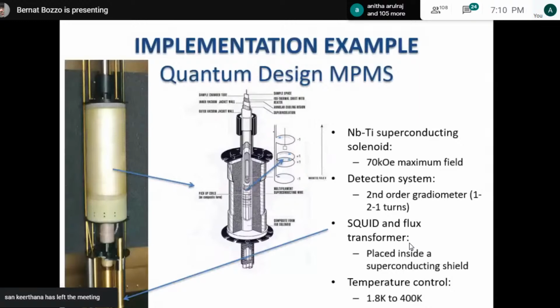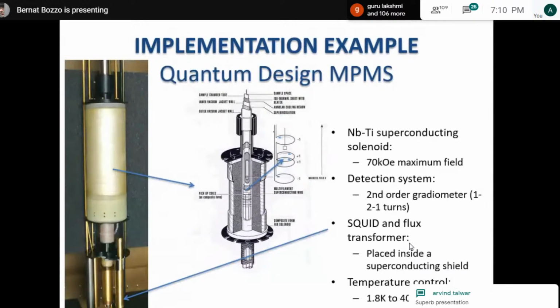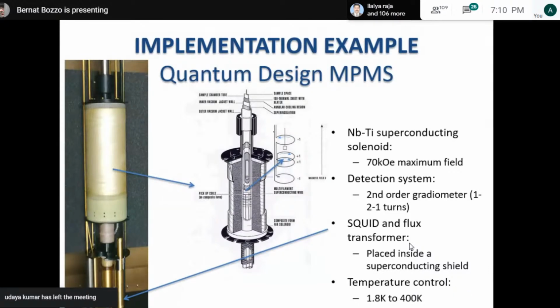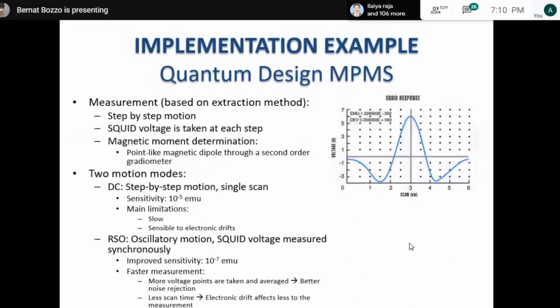In this system, the solenoid is made of niobium titanium and is able to apply 7 Tesla, and the temperature control of the system is from 1.8 Kelvin to 400 Kelvin. Basically, we treat the signal of the sample through this second order gradiometer by step-by-step motion, and at each step we take the SQUID voltage.